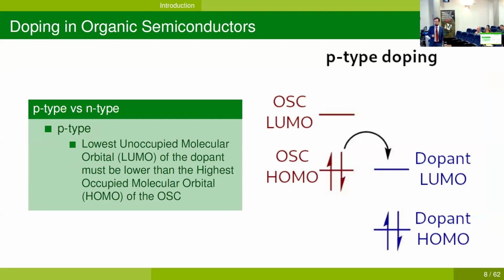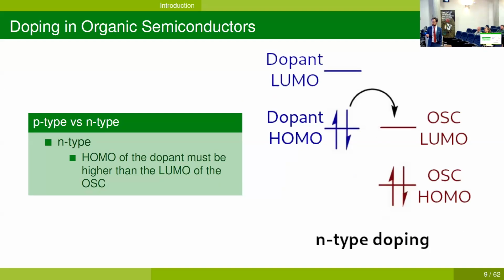When we talk about organic semiconductors, we need to talk about doping if we want to achieve high electrical conductivity. So p-type doping occurs when the lowest unoccupied molecular orbital, or LUMO, of the dopant is lower than the highest occupied molecular orbital, or HOMO, of the organic semiconductor, as is depicted here. On the other hand, n-type doping occurs when the HOMO of the dopant is higher than the LUMO of the organic semiconductor.